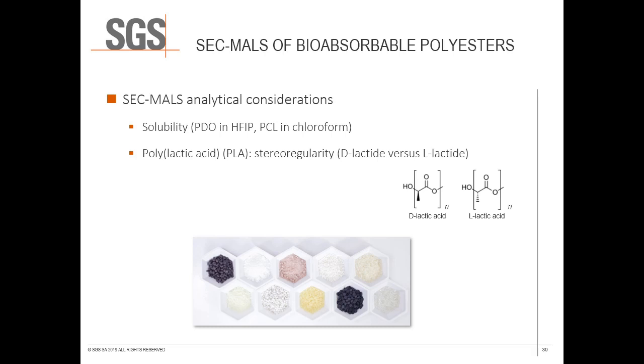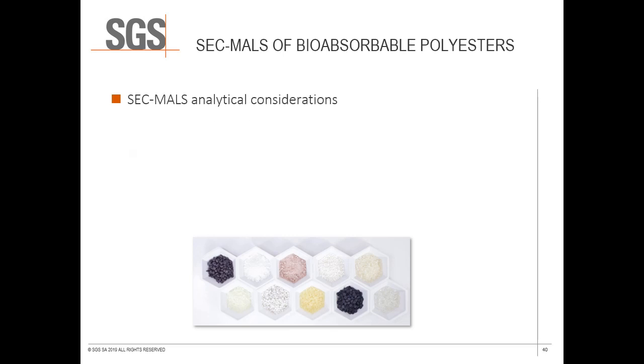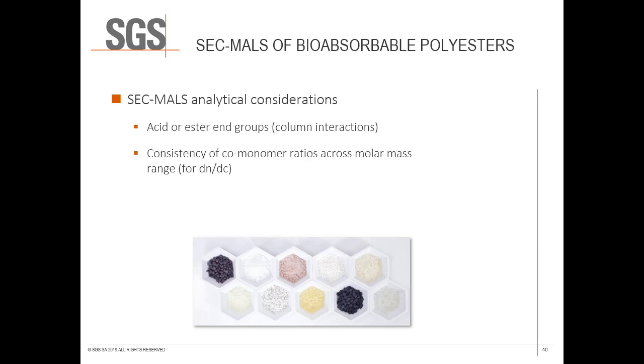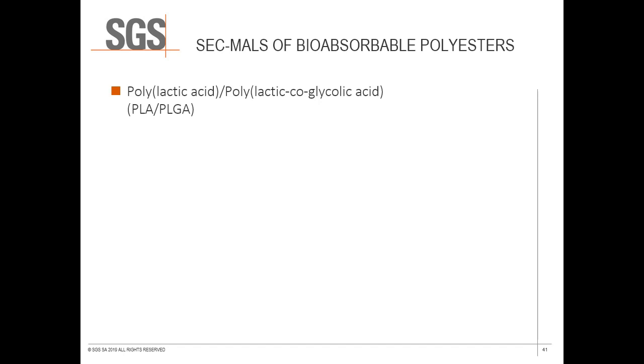Another thing to consider that is affected by monomer composition grouping as well as the manufacturing process is sample crystallinity. Crystalline samples may require heat to dissolve, but most bioabsorbable polyesters are also at risk of hydrolysis, and so caution must be exercised. If significant heating is to be used, a heating time degradation study is recommended. Some polyesters may have acid or ester end groups, and acid end groups can cause significant column interactions if preventative measures are not taken. Copolymers like PLGA pose another challenge, and that is the consistency of the comonomer ratios across the molar mass range. If inconsistent, then the differential refractive index increment may be different at various points across the polymer peak. This would contribute to error in molar mass calculations and must be considered from the start of an analysis. As an example bioabsorbable polyester analysis, we'll look at polylactic acid, polylactic coglycolic acid copolymer resin.